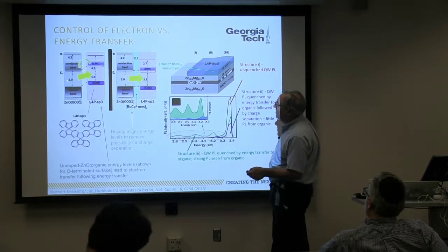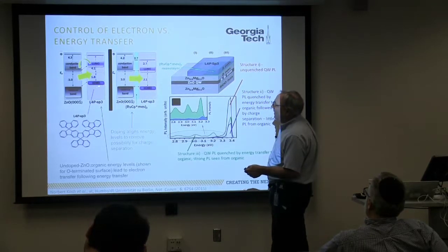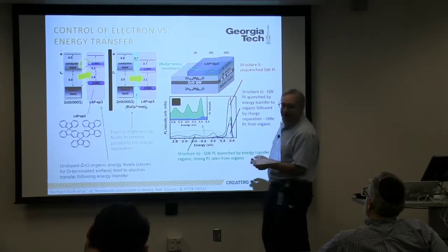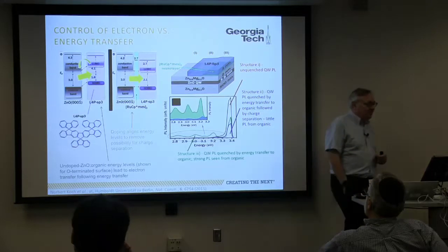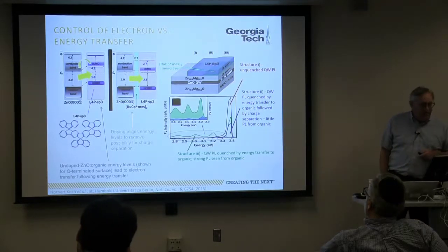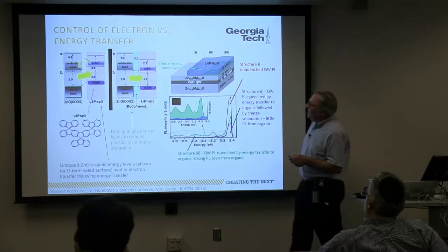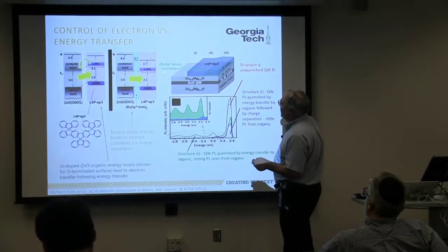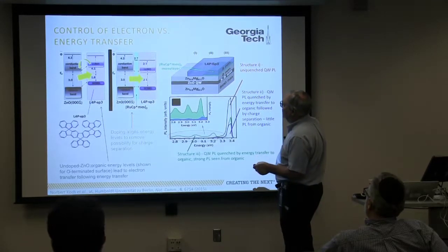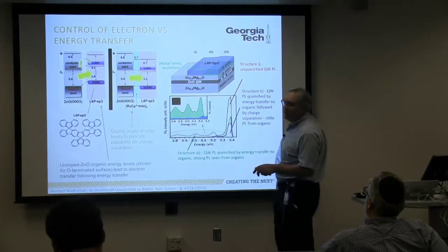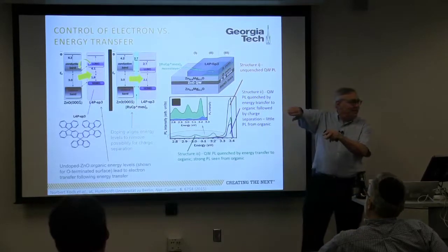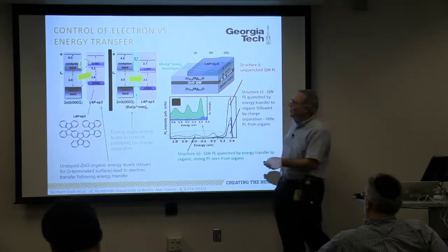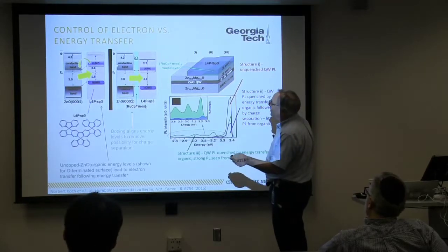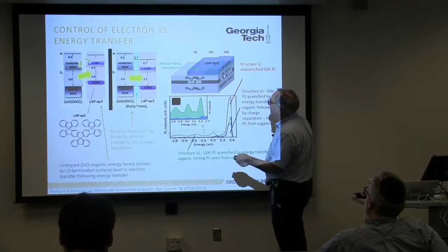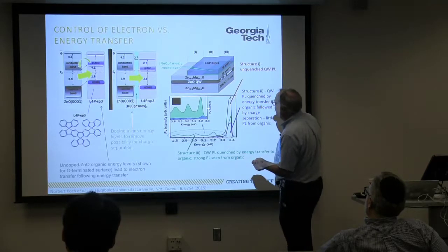And as a consequence, when they did the energy transfer to this material to create a hole here and an electron there, they get a back electron transfer to the conduction band of the zinc oxide, which quenches the luminescence. When they put down a monolayer of this ruthenium compound in between, it creates just a touch of band bending. It shifts those bands up such that now the conduction band is well aligned and the back electron transfer doesn't occur.